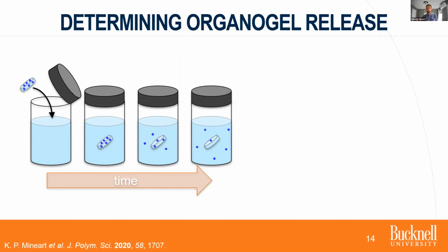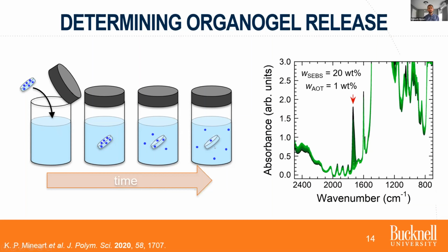One is from release or drug diffusion in hydrogels, which uses this kind of release experiment where we take a gel loaded with AOT and drop it in pure solvent. In this case, we match our gel, so this is aliphatic mineral oil. And then over time, the concentration gradient drives the AOT reverse micelles from the gel to the surrounding liquid. And then to analyze the remaining concentration of AOT in these gels, we actually use FTIR spectroscopy in transmission mode through the gel. And there's a very well-resolved carbonyl peak that corresponds to groups in AOT and none of the groups in the polymer. And so we can track that peak absorbance over time.